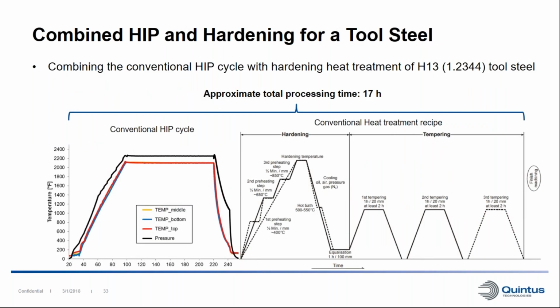Here we're looking at a combined HIP and hardening for a tool steel. So this is pretty much the conventional process I've shown here. So we have a HIP cycle, and then we have the solutionizing cycle, and then 3-time tempering here, all according to the conventional heat treatment recipe. And an approximate total processing time of this is 17 hours. That's just cycle time, no wait time in between the different steps.